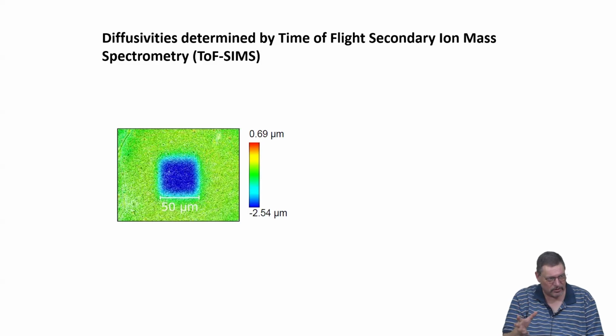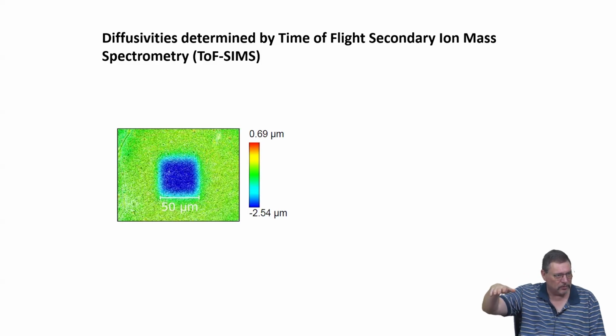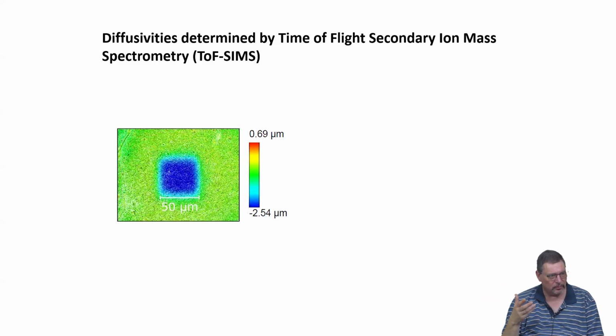If this fraction is higher, then your applied isotope will diffuse in, but it will very quickly reach the level of the base material. Then you cannot measure diffusion anymore. So you want to use a stable isotope for these measurements, where in the natural material its abundance is as small as possible. So you have a large contrast between the applied isotope diffusing into your material and the base level given in your normal material.